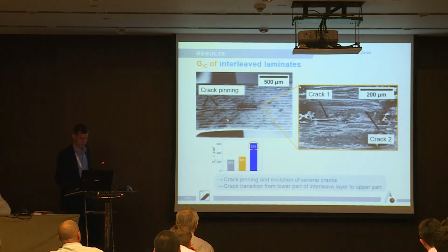You can see the crack is growing, and you can also see it's undulating, and at some parts there are new cracks starting. So here, for example, there's a transition of the crack, and the crack is starting at another point of your material. So you can also see this in the other pictures at low magnification. Here you see the first crack, second crack, and we call this crack pinning. Here also with high magnification, you can see the first crack stops at this interleave and starts to grow at another point.